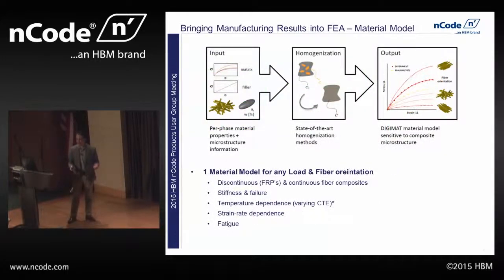The way that we deal with that is we start by looking at the material at a level deeper than the homogeneous composite level. We start with a material model that has a description of the matrix by itself, the fibers by itself, and a description of the fiber orientation: how long they are, how many fibers there are. We can then take all that information and homogenize it together to predict what the composite response is going to be. So the point is that we can have one material model where for any load and any fiber orientation, we can predict the stress-strain response and the strength of the material.